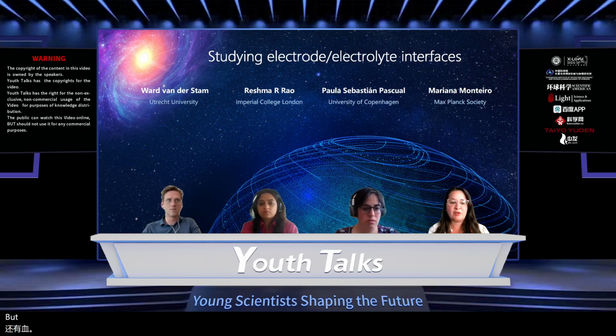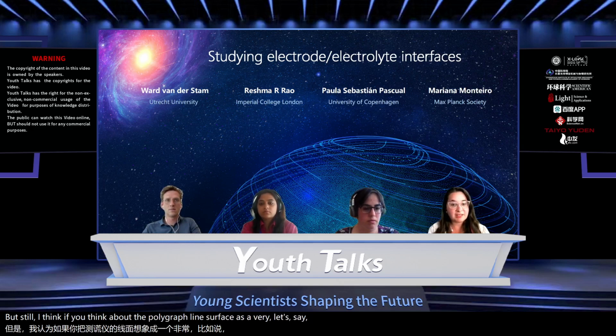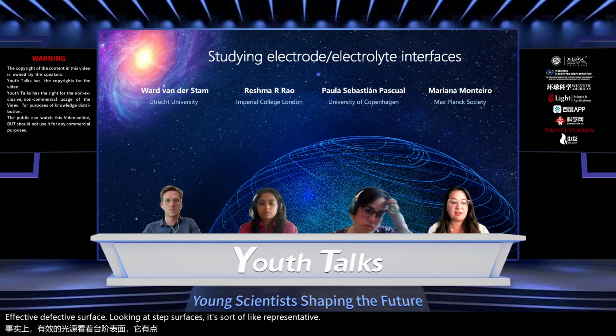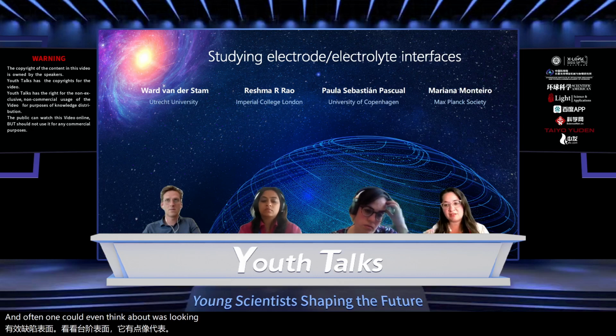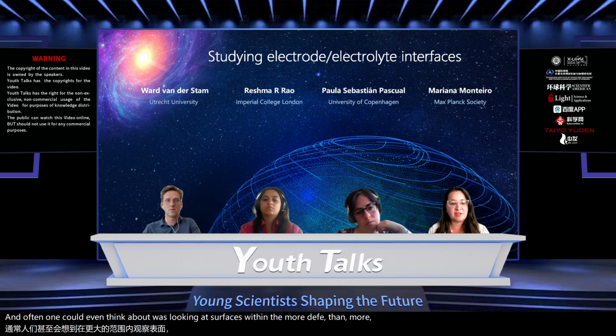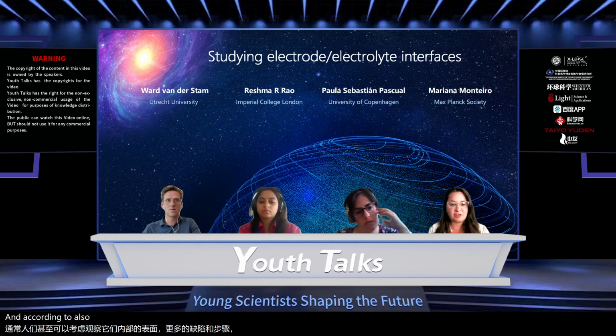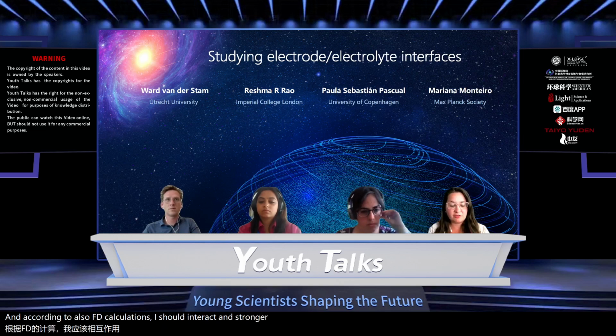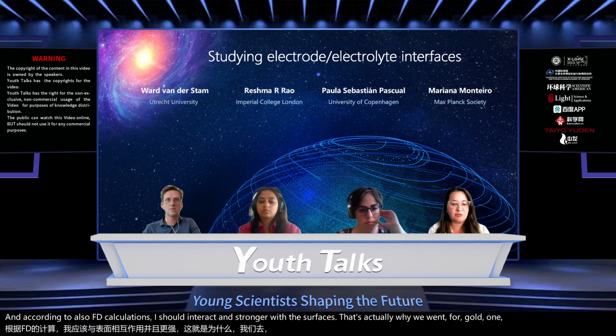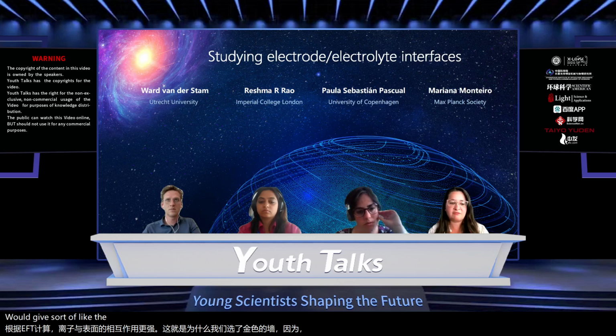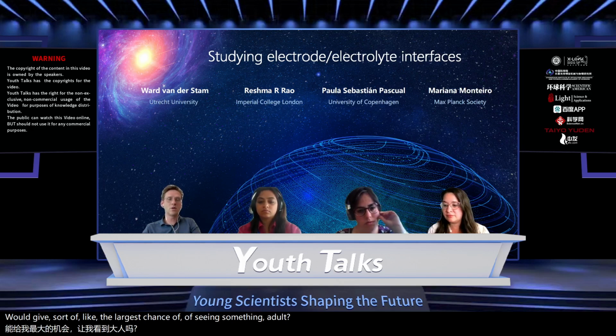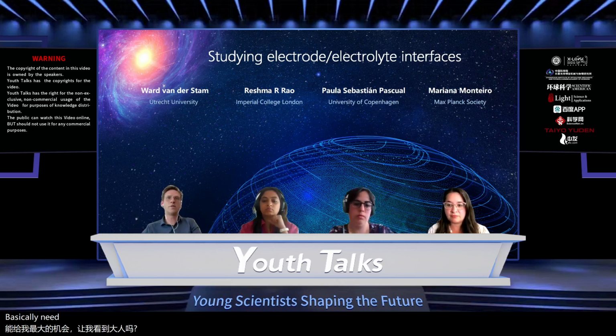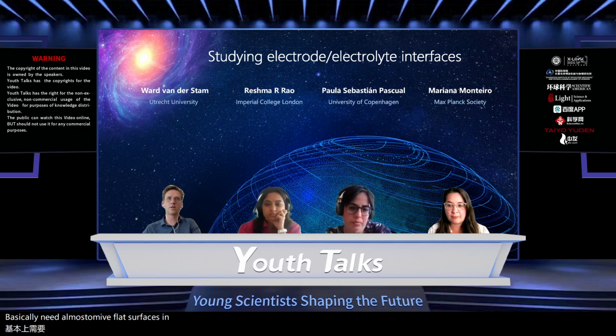But still, I think if you think about the polycrystalline surface as a very defective surface, looking at stepped surfaces is sort of representative enough. And one could even think about looking at surfaces with more defects and more steps. According to DFT calculations, ions should interact even more strongly with those surfaces. That's actually why we went for gold 100, because that would give the largest chance of seeing something at all. So you basically need almost atomically flat surfaces to be able to do this. Yeah.